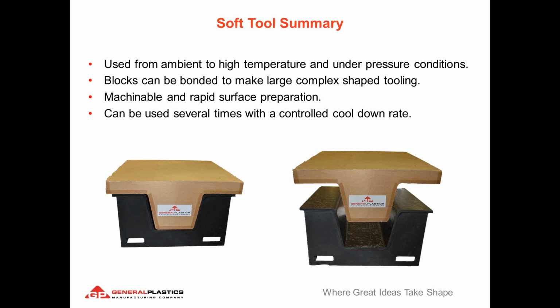So in summary, used from ambient to high temperatures and under different pressure conditions, FR4700 is a great solution for these higher temperature cure profiles. The blocks can be bonded to make large, complex shaped tooling. Another cost savings advantage to using foam is you can cut your blocks to minimize the amount of material you have to machine off afterwards. It is machinable, with rapid surface preparation using a release film instead of the filler and surface sealers. And also with controlled cool down rates, we've shown that several tools can be made off of these parts. Again, a lot of that is very dependent upon your cure profile and cycle and the complexity of the shape of the tool.